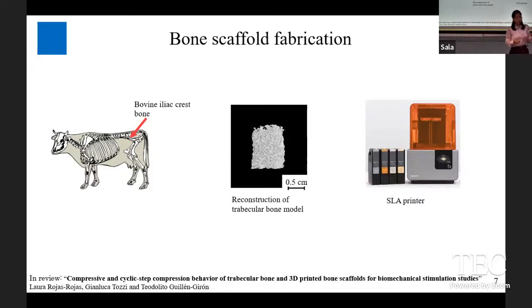We wanted to reproduce as close as possible the trabecular bone morphology. So in that sense, we took a sample from an iliac crest bone from a cow. We imaged the bone using microcomputed tomography. And then with the image stack from the microcomputed tomography, we did a reconstruction of the bone model, and this reconstruction was then printed using a stereolithography technique, or in short, SLA, using a biocompatible resin.